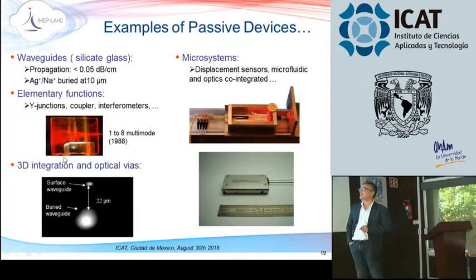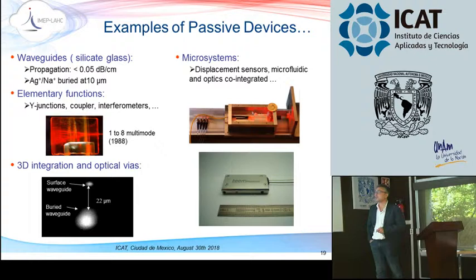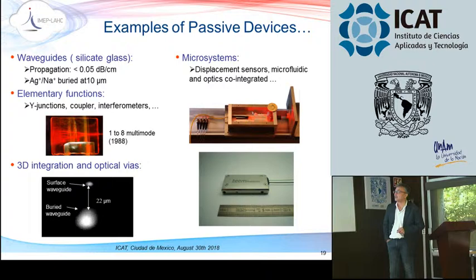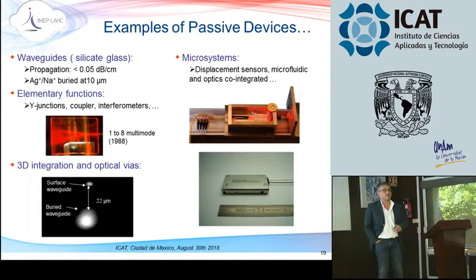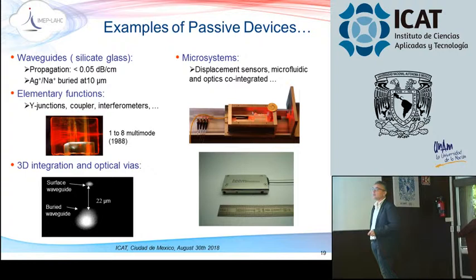These are typical characteristics of the waveguide. So the losses are quite low, 0.05 dB per centimeter. And they are made by silver-sodium ion exchange that is buried at 10 microns. So of course, with this, we did elementary functions. So this is the first device ever made. It was in 1988, and it's a 1-to-8 splitter. We'll talk about that later.